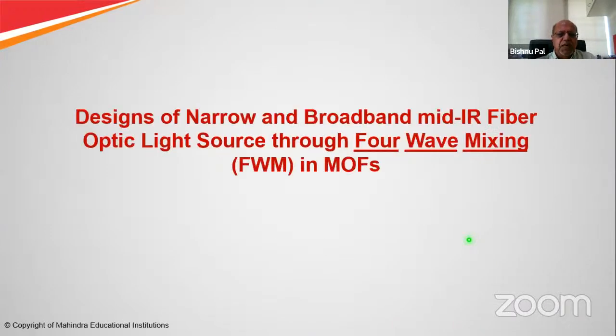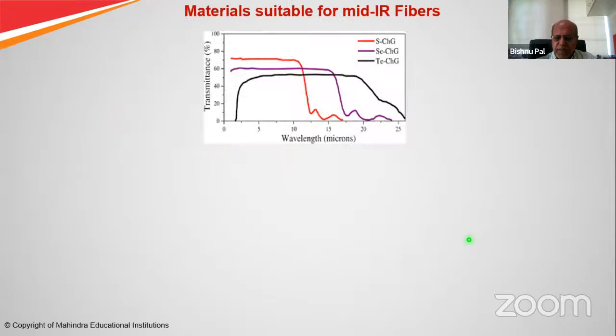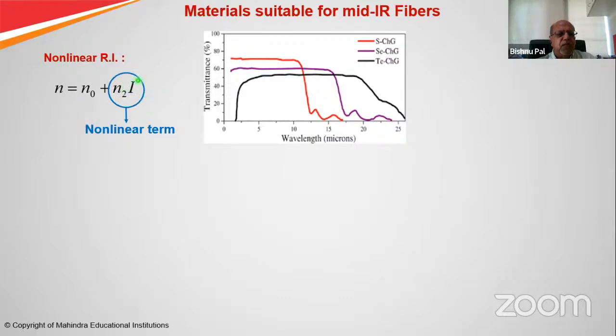Now I come quickly to specialty fibers for mid-IR application, where we again exploit a nonlinear effect, four wave mixing. It was mostly the PhD work of my student Ajanta Bhatt, who is right now at ETH, Switzerland. This represents the transmittance as a function of wavelength for different materials suitable for mid-IR fibers. Also, as many of you would know, the refractive index of a nonlinear medium can be represented by a linear part and a nonlinear part, which is the nonlinear contribution to refractive index, with a dimension of inverse intensity, multiplied by the intensity of the propagating light. So the effective refractive index seen by the propagating light would be given by this linear part, and this is the nonlinear part.